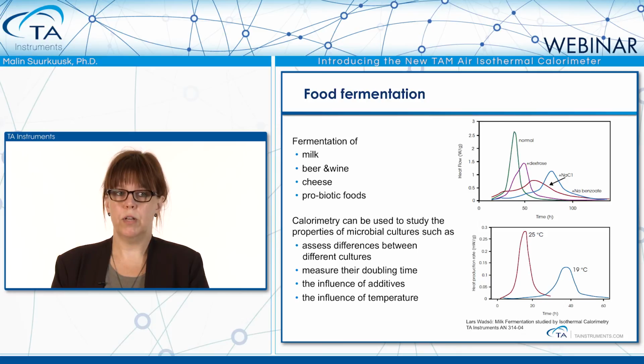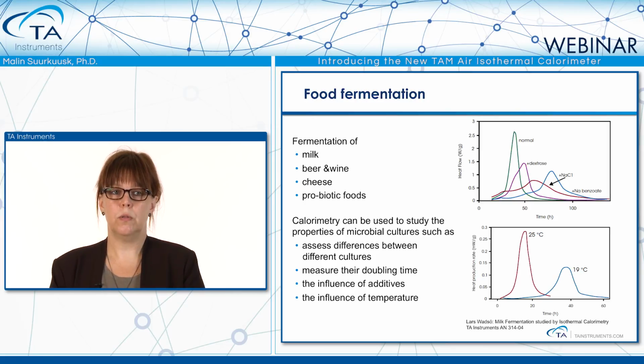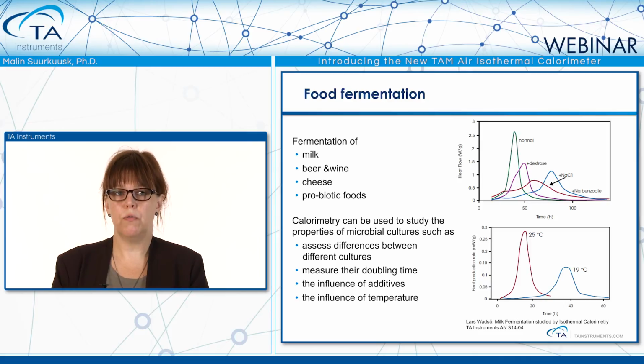So if we take the influence of additives, we can see in the top graph where milk is fermented and there are different sugars and salts and preservatives added, and we can see how the fermentation process is changed in time when adding these additives to the milk. In the bottom graph, it's shown the fermentation process as function of temperature. So the same milk fermentation is done at 25 and 19 degrees, and we can see that the fermentation process is faster at higher temperatures.